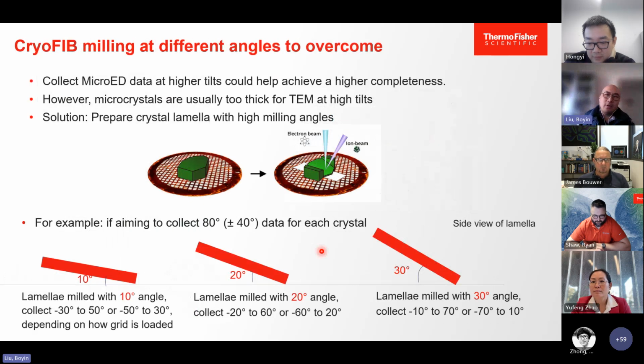So one of the solutions to overcome this preferred orientation is to try to collect high tilt data. But unfortunately, microcrystals are usually too thick for TEM at high tilts. So now cryo-FIB comes to the rescue. You can actually prepare crystal lamella with different milling angles, and then try to get information at different tilt angles.